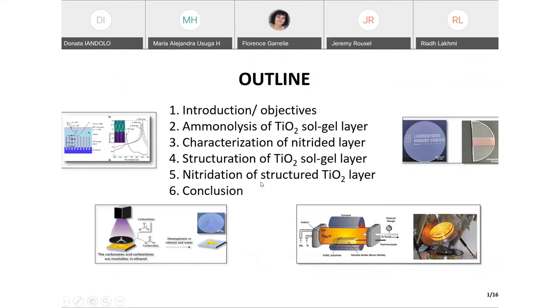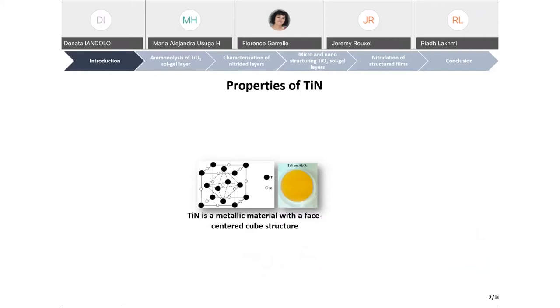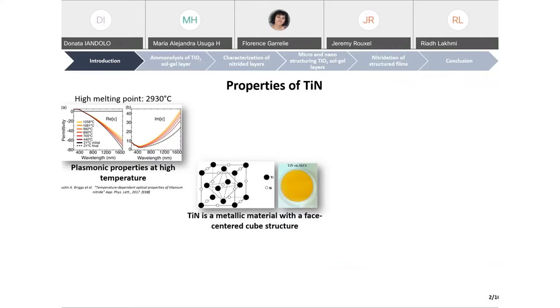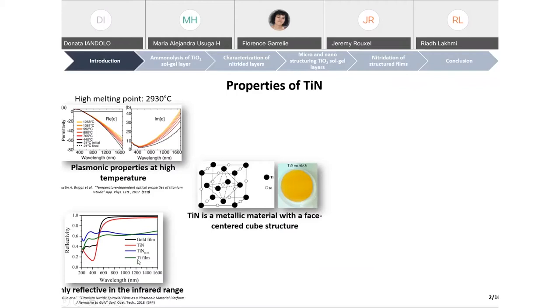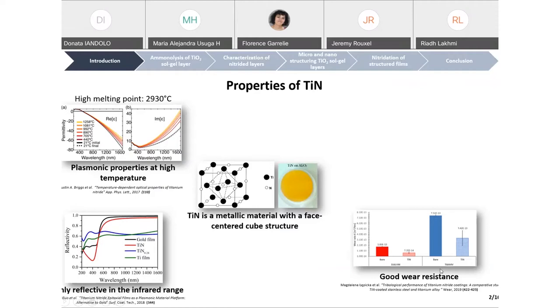Titanium nitride is a metallic material with a face-centered cubic structure. It has a yellow, golden appearance. It has plasmonic properties at high temperature and a high melting point, so it is interesting for high temperature sensor applications. Titanium nitride is highly reflective in the infrared range. Like gold, titanium nitride can replace gold under certain conditions, particularly in conditions where gold can melt or dissolve. This material also has good wear resistance. Sometimes it is used as a protective coating exposed to wear, and it has good electrical properties.